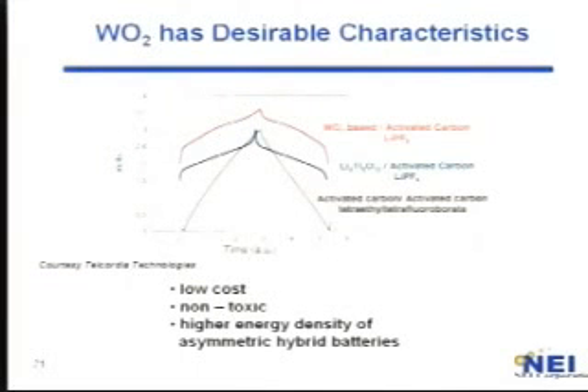Well, as my previous speaker mentioned, the use of lithium titanate actually reduces the voltage of the battery. So for most of the devices I showed, the asymmetric hybrid device, the voltage is around 2.15. So if you're looking for a device which has a high, fast charge rate, and you want to increase the energy density of the device, you have to jack up the voltage.